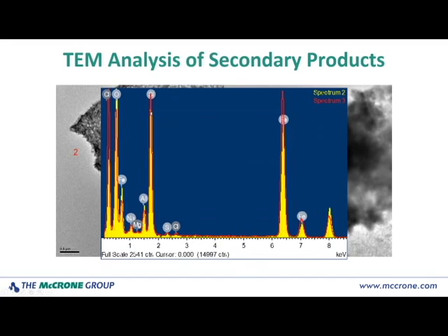So if you look at these spectra which have been normalized on the silicon peaks, you can see that you have a lower iron to silicon ratio for the yellow, the spectrum 2. So two distinctly different products forming, but possibly also an indication that you've got a process going on of continuous dissolution of glass, reaction of glass with the iron-containing API, and then forming a product that may eventually finalize at a given iron to silicon ratio. But certainly something going on beyond just glass delamination.